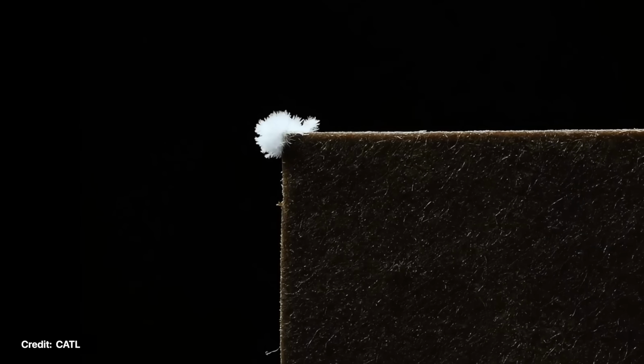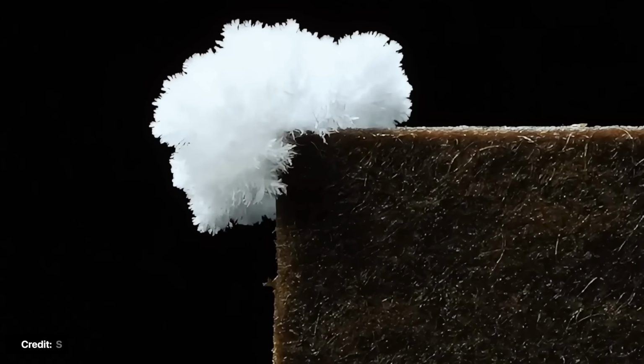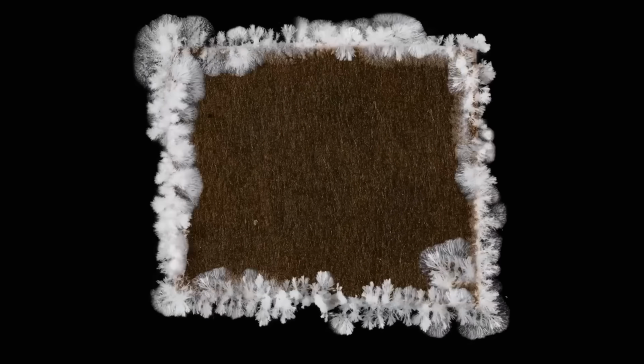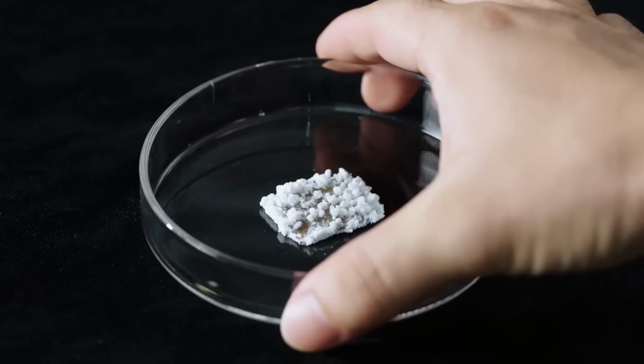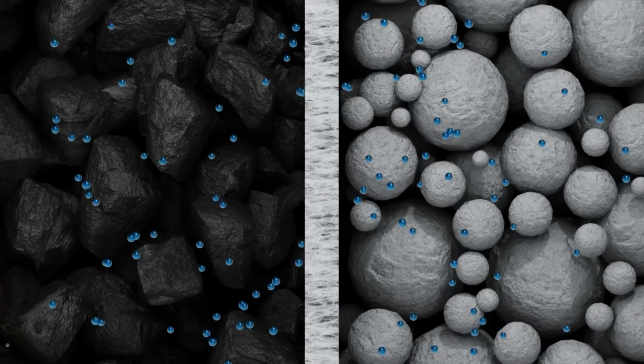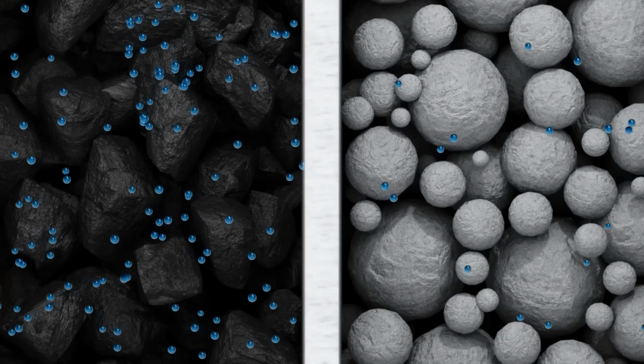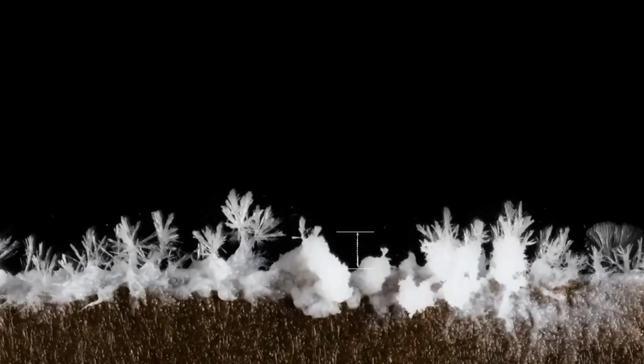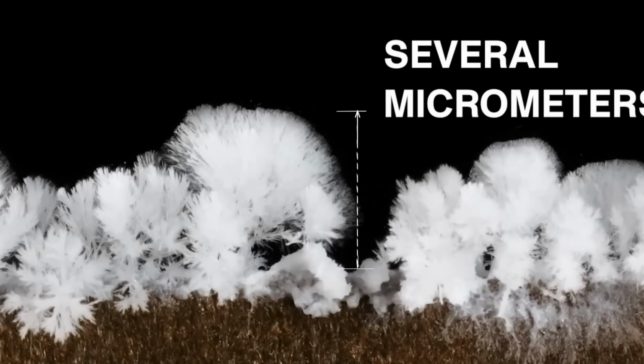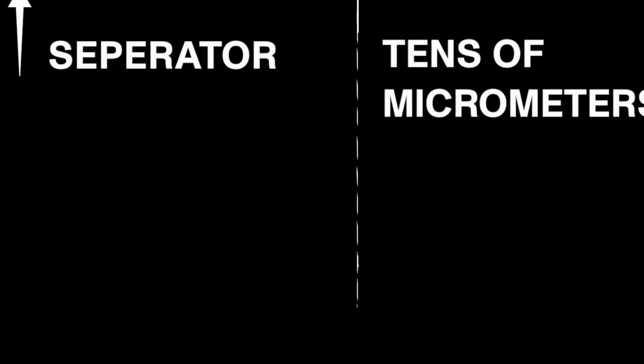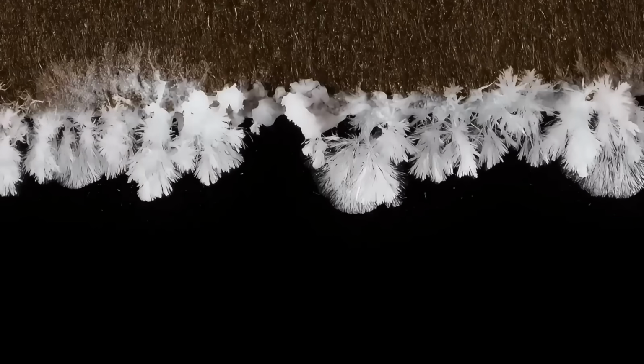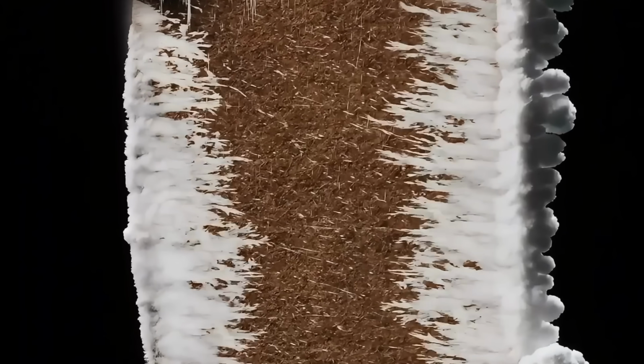One of the biggest limiting factors in battery performance and lifetime is the formation of lithium dendrites, microscopic needle-like metal structures that grow during charging. When lithium ions plate unevenly onto the anode, especially at high charge rates, these dendrites can extend across the electrolyte toward the cathode. In liquid electrolyte cells, dendrites can eventually pierce the separator, creating an internal short circuit, rapid heating, and in worst cases, thermal runaway. To prevent this, modern batteries deliberately limit charging current, operate within narrow temperature windows, and avoid full lithium metal anodes altogether.